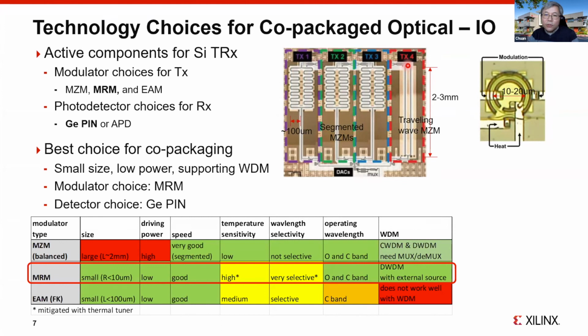Another way is to use a traveling wave design. Basically you have a transmission line, so your electrical signal and optical signal travel down the modulator simultaneously if their speed is roughly matched. So you get a traveling wave modulator. But either approach requires a pretty long device, on the order of 2 to 3 millimeters in length. That obviously takes up a lot of space on the die.